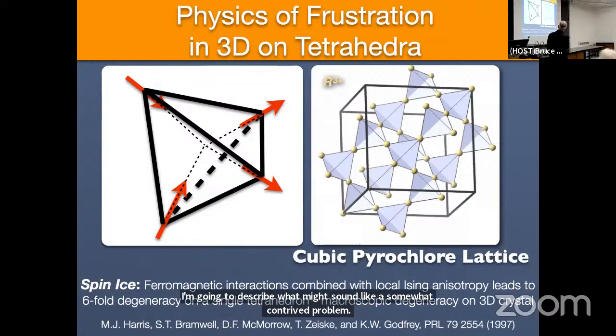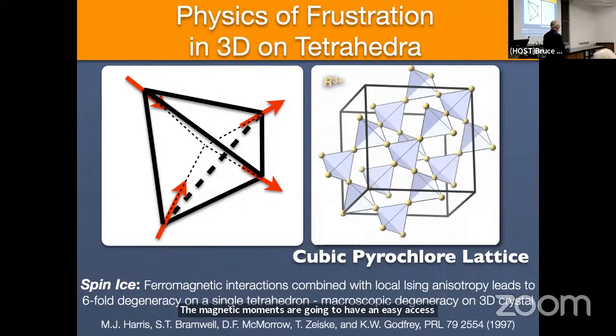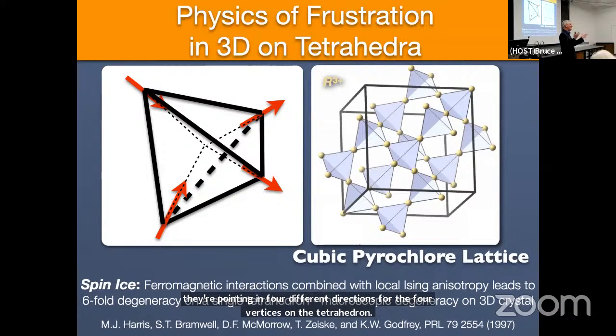Okay, I'm going to describe what might sound like a somewhat contrived problem, but I'm going to have the magnetic dipole moments interact ferromagnetically with respect to each other, which means that they would actually like to all point in the same direction. Okay, but the magnetic moments are going to have an easy axis, and the easy axis for the 4 vertices of the tetrahedron are not collinear with respect to each other. So the easy axis for these dipole moments points directly into or out of the tetrahedra, and they're pointing in 4 different directions for the 4 vertices on the tetrahedron. So the system would like to form a ferromagnet.